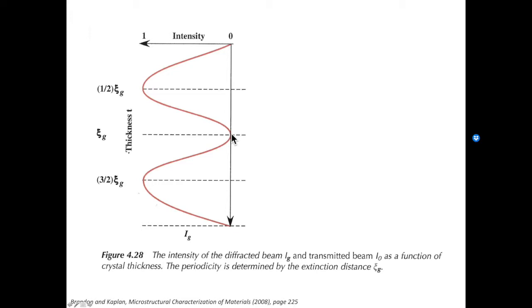This kind of observation is somewhat unique in TEM and you don't really see it in X-ray diffraction. The reason is that scattering events in X-ray diffraction are mainly kinematical, while in TEM, due to the sample thickness, the dynamical effect can be pretty dominant. Further increasing the sample thickness, the intensity profile continues to follow the sine-square function.